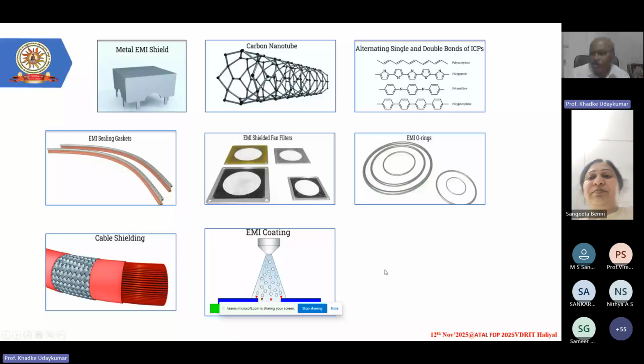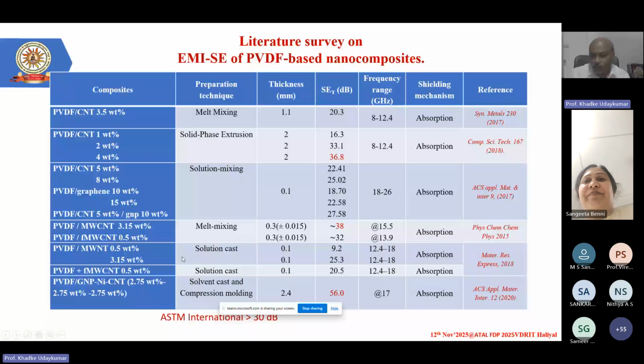Well, these are the samples that we used, and whatever I have shown in red color. Now you see that PVDF mixed with carbon nanotube. This is multi-wall carbon nanotube with different concentrations: 1 weight percent, 2 weight percent, and 4 weight percent. What we got when we mixed 1 weight percent, this is without ion beam. We modified the properties of the material just by the conventional mixing method. And when 1 weight percent was mixed, we got 16.3 decibel EMI shielding. When 2 weight percent, 33. When 4 weight percent, 36, which means that as a function of concentration, the shielding effectiveness is increasing.